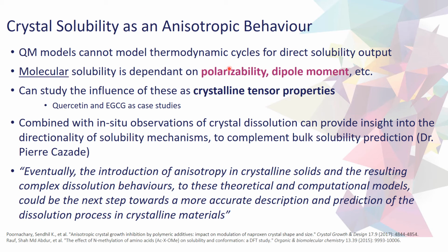So the models that I've been talking to you about today, using density functional theory, quantum mechanical based models, we can't directly model solubility with this because we can't study temperature effects. So we can only look at crystals pretty much at 0 Kelvin. And to get our full solubility curves, we need to study phenomena over a range of temperatures.